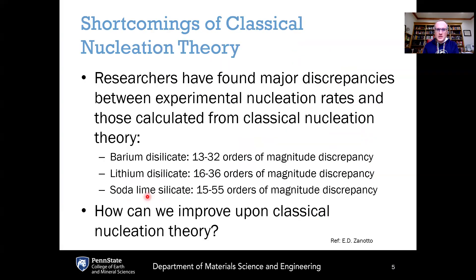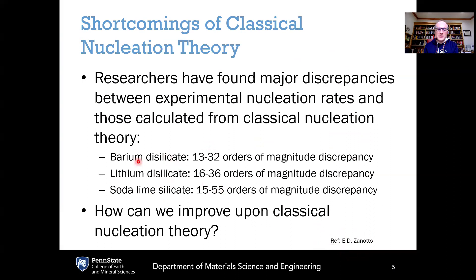Some of the shortcomings of classical nucleation theory also include some rather major quantitative discrepancies between what's predicted from classical nucleation theory and the actual measured nucleation rates. These are some extreme cases noted by Professor Edgar Zanotto from the Federal University of São Carlos in Brazil. For systems like barium disilicate, lithium disilicate, and sodalime silicate, the predictions are many, many orders of magnitude off compared to the actual data.